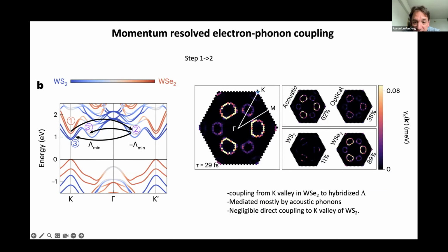So we initially excite at the K valley of WSe2. And what these color plots are essentially encoding is the rate for coupling to various points in momentum space. These bright regions correspond to 3 of the 6 allowed lambda values of the structure. So this first calculation is showing that there is direct fast coupling to this lambda valley, this hybridized structure.